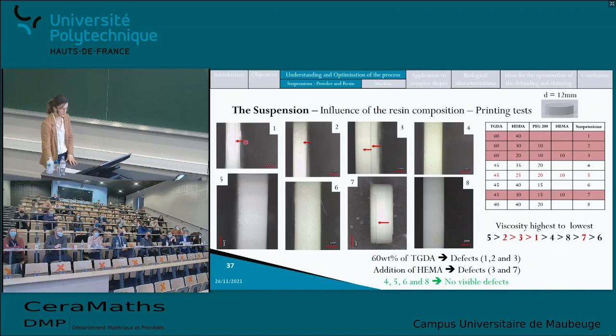However, the only sample that I wasn't able to explain here was sample number 5, because it was printed with a suspension with a very high viscosity and had no defects here. So I decided to do more experiments, and I observed the samples with SEM analysis. I did this SEM analysis on the cubes with holes.